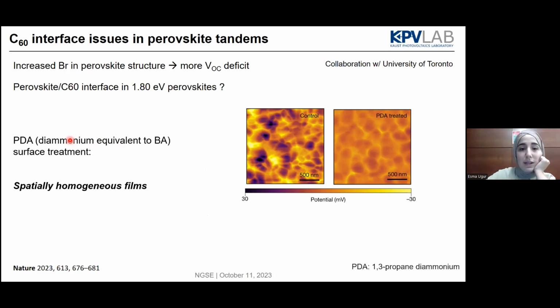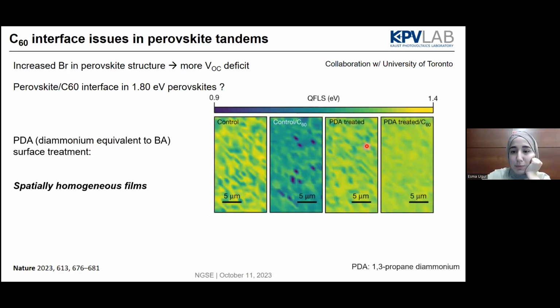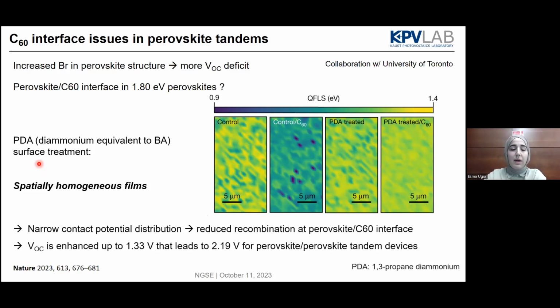So what happened at the end when you do the PDA treated one, it becomes slightly more homogeneous, let's say, but when you put the C60, you will see really a huge difference compared to the control one. So what we need is to have this spatially homogeneous film on the perovskite surface that will narrow this contact potential distribution, therefore reducing recombination at that interface.